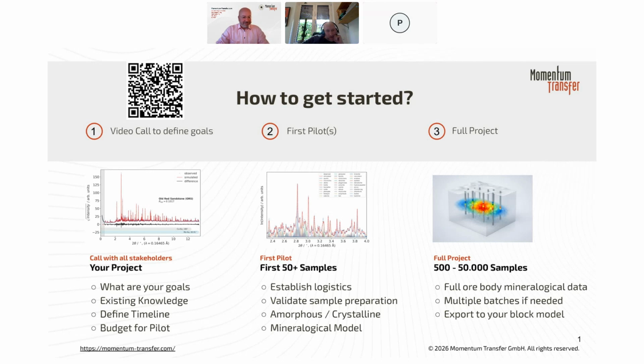Can this technique quantify the mineral intensity? I assume by mineral intensity you mean the mineral concentration. In that case, yeah, absolutely. For some clay minerals, particularly more crystalline ones, like kaolinite in some cases which comes in a very crystalline form, and different chlorites, for instance, which can be very crystalline, we can model the clays in the same way that we do all of the other phases with a crystal structure.